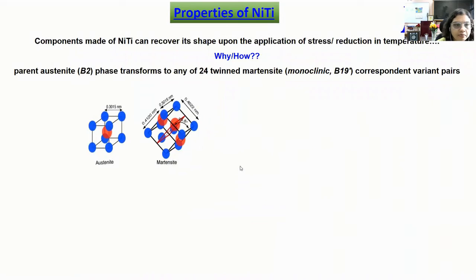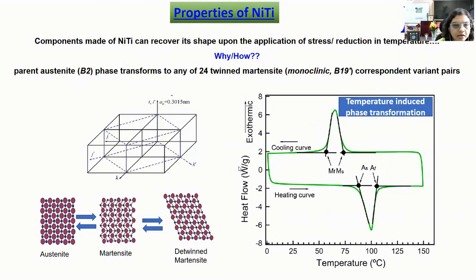Now that leads to the differences in the exact temperature when we are converting the high symmetry to low symmetry versus when we are converting the low symmetry to high symmetry. It is always energetically favorable to move to the high symmetry structure. So we cannot have the same amount of energy required for the conversion of high symmetry to low symmetry and low symmetry to high symmetry. That leads to a variation in the values of the exact Ms temperature or Af temperature. So you can say that due to loss of some energy, the temperature variation is coming due to deformation. Yes, yes.